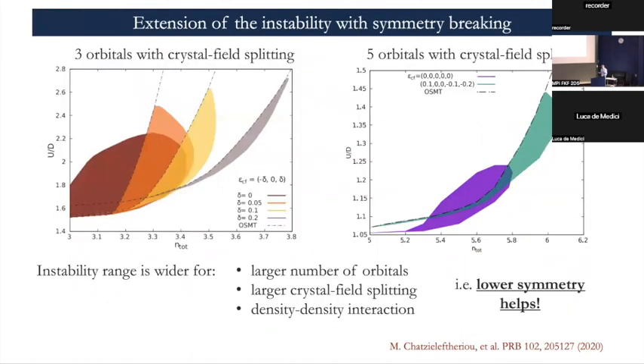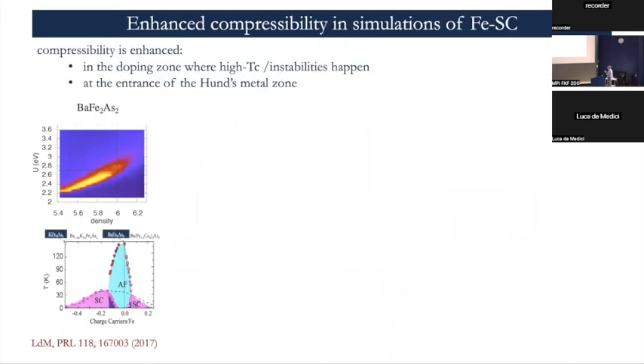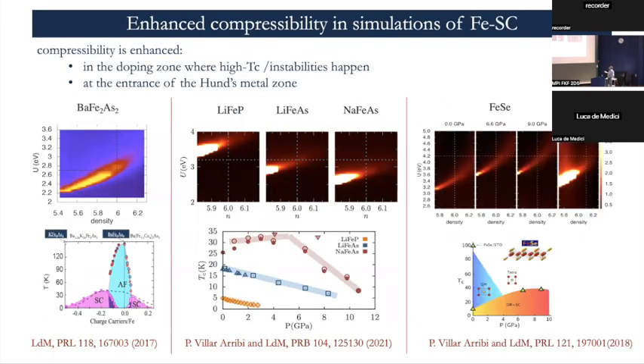Now, the last part, very quickly, if we go multi-orbital, if we go realistic, I go back to my compressibilities, and one can easily show in models that the more you go realistic, the more the zone of phase separation due to the enhanced compressibility increases, both if you break any symmetry or if you add many orbitals. And indeed, we could show in all iron-based superconductors that there is a zone that they call a mustache coming from the half-filled Mott insulator, but extends all inside the interaction-doping plane until reaching the interesting part where the symmetry breakings and the superconductivity happen.